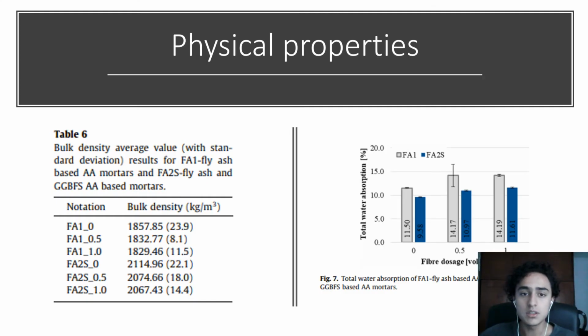Physical properties. A decrease in the density and an increase in the water absorption of the samples were reported when using hemp fibers. However, the densities increased on the mortars with fly ash. In the figures, you can see the densities and amount of water absorption according to the fiber dose.